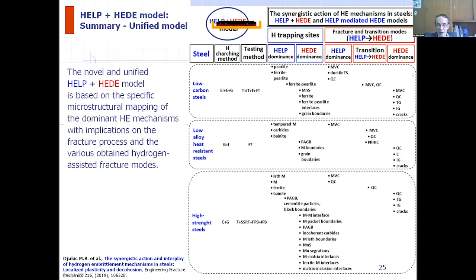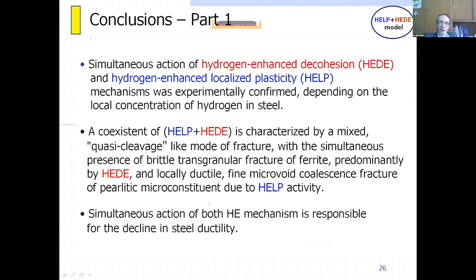So in our review paper, we summarized the novel and unified HELP plus HEDE model, which is based on a specific microstructural mapping, as shown previously, of the dominant hydrogen embrittlement mechanism with implication of the fracture process and the various obtained hydrogen-assisted fracture modes. We listed here hydrogen trapping sites responsible for HELP dominance and for HEDE dominance, and also the corresponding fracture modes and transition modes, which are related to the dominance of the HELP mechanism and the transition from HELP to HEDE dominance, and finally the HEDE dominance, which you can see here for different types of steels. Finally, conclusions of our presentation.